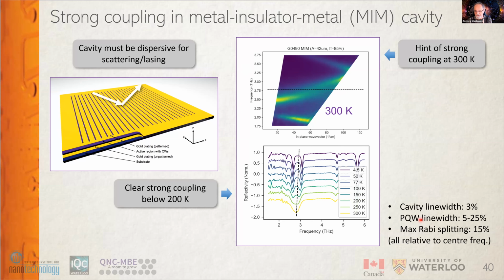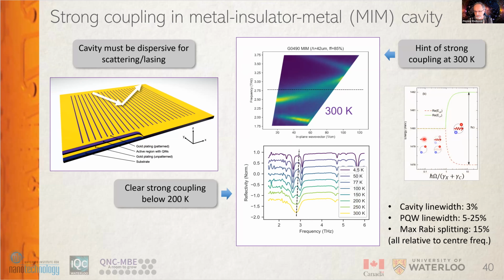And these are the scans for different temperatures. And you can see that the Rabi splitting, which is what we were after, is retained definitely down to 200 degrees Kelvin. So this is really remarkable, and I think we can work with that towards the laser.